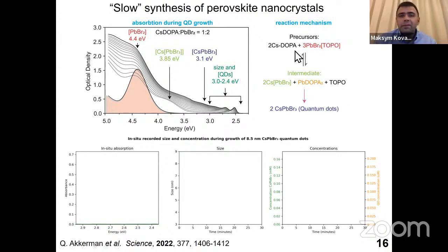Then, as you mix them, they slowly start to react, forming lead DOPA, which is a phosphinate of some kind, doesn't matter too much, and an actual intermediate. So now you form this cesium lead bromide, but not a lattice, but a conglomerate of ions, which is cesium plus and lead bromide 3 minus. It's a 3 nanometer large chunk of ions, which are pre-aggregated, and then they slowly recrystallize into the nuclei of the nanocrystal, and then you form a nanocrystal. So that's our current understanding of the mechanism.